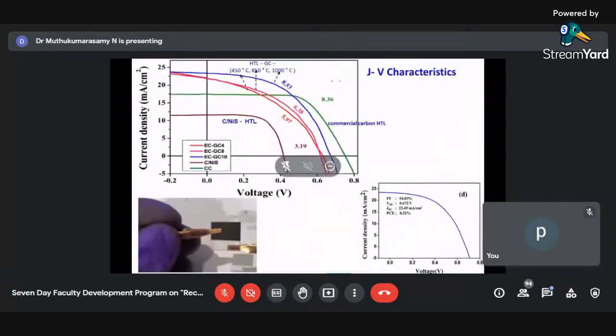And we fabricated a solar cell where this carbonaceous layer was used as a hole transporting material, you can see, and we went for the doctor blade method to have that layer. And we got an efficiency of 8.53% for the carbon which was annealed at 1000 degrees centigrade, because it was a highly graphitized type of carbon, and we got a very good efficiency of 8.53%. And this was published in Nature Scientific Reports. And you can see the solar cells which we have fabricated, the methodology which we used to fabricate solar cells. Even the solar cell which we fabricated by using commercial carbon was only 8.36%.